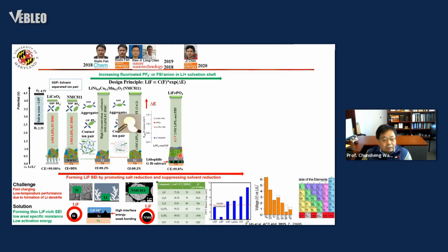As we talk here, this is universal, not only for lithium. It should work for silicon, also. Then we check silicon with the same electrolyte, and we put in micro-size silicon, because if this concept is right, the crack doesn't matter. So we can use micro-size. We tried micro-size 30 micron, and we can get a Coulombic efficiency of 99.9. Because for silicon, everybody believes it should be nano, and micro-size was never successful. Based on this concept, we make micro-size silicon, 30, 40 micron, that can cycle very well.